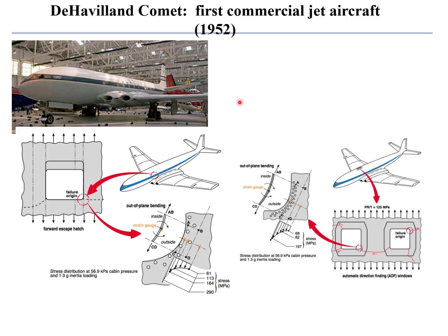And so there were catastrophic failures of these aircraft within two years of being placed into service. They would simply disappear somewhere over the Atlantic Ocean. They traced the failures back to fatigue cracks growing from stress concentrators associated with those windows and propagating through the fuselage until during pressurization they would reach a catastrophic stress level.